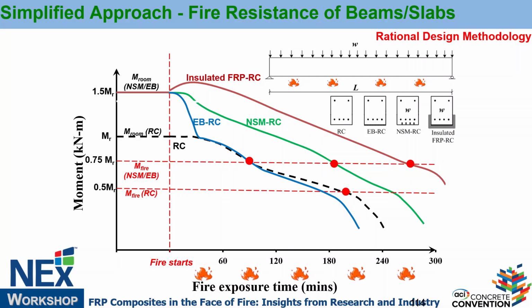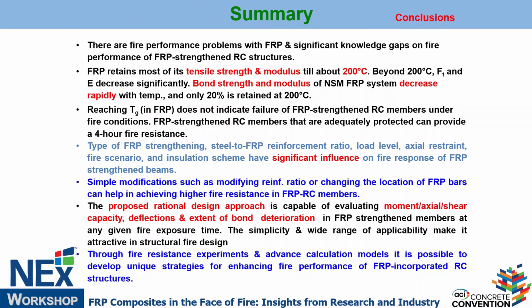Now, if you put in NSM, look at this here. Why? Because of the cover thickness you provided, the temperatures increase slowly in NSM. So it retains more strength. So it fails somewhere here. But if you insulate the same EB, which failed here, you can push it to wherever you want, depending on the insulation thickness and its properties. So this is how the fire behavior of these beams is.